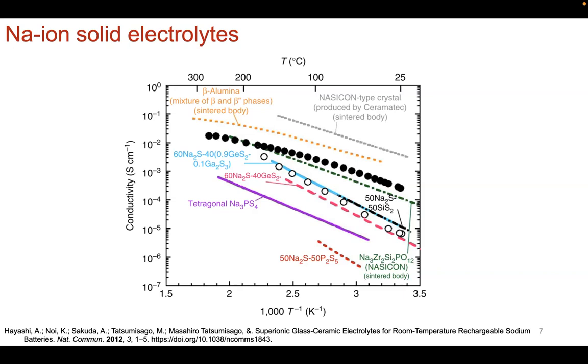What we've done conventionally with solid state synthesis, people have tried to do with liquid phase or solution phase type synthesis to get these metastable structures that you wouldn't normally get. And when I say metastable, I mean, if you do conventional solid state syntheses, you access thermodynamic equilibrium phases that you can only get at higher temperatures. But if you want the high ion conductivity properties of those high temperature phases at lower temperature, you have to develop a different synthesis or some way of stabilizing these structures, right?